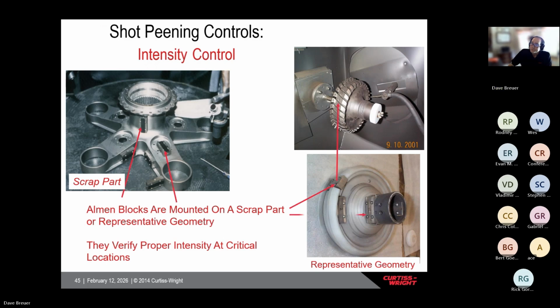For some components that are more critical, the best almen fixture is a scrap part. Wherever you see these blocks, 1, 2, 3, 4, 5, that's where almen intensity is being measured. Almen intensity is measured before a load of parts, so that if it's not reading properly, you can make some changes to the process.